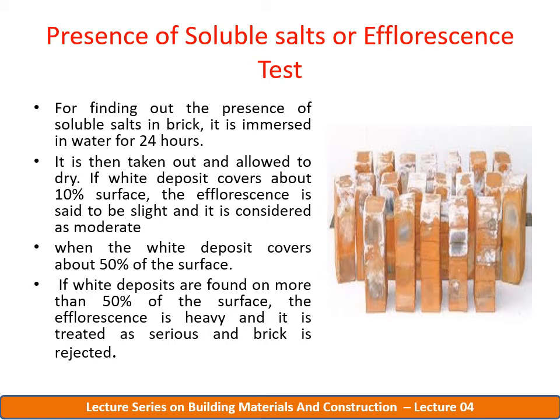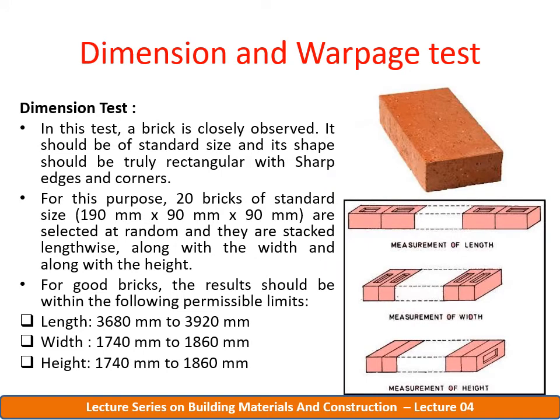So after immersing for 24 hours, the bricks will be taken out and allowed to dry. If the white deposit covers about 10% of the surface, the efflorescence is said to be slight, and beyond that it is considered moderate. So next is the dimension and warpage test.